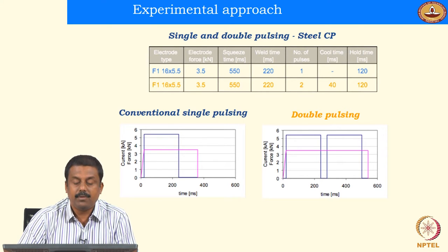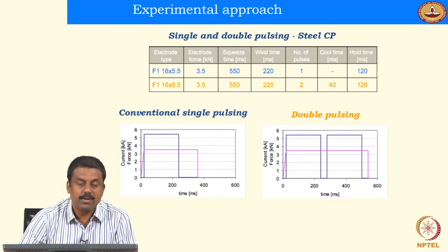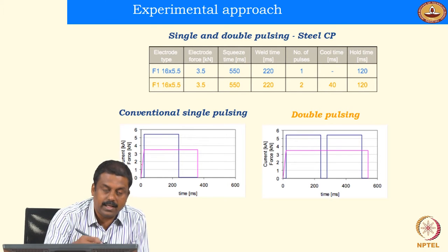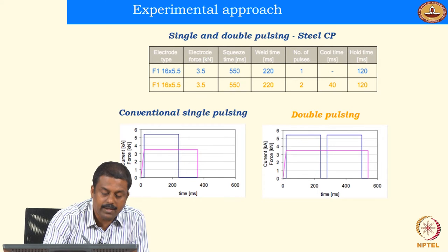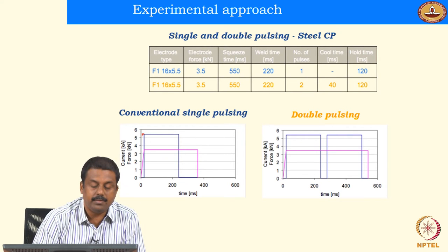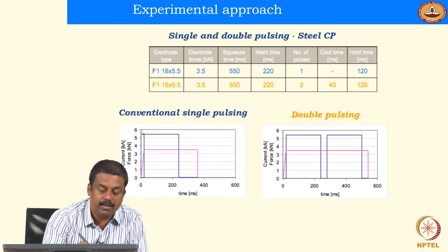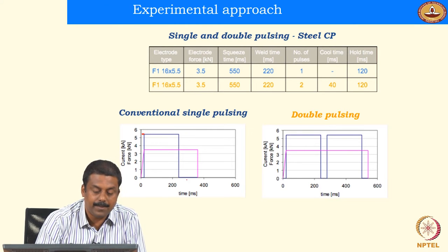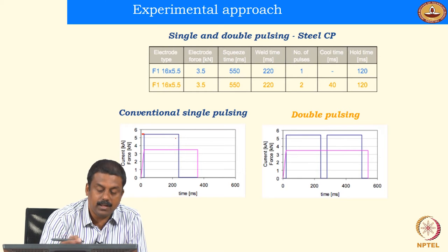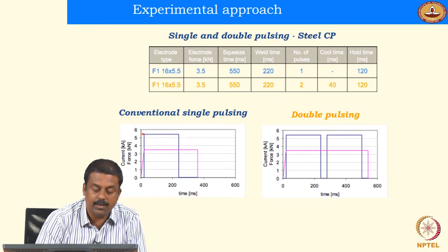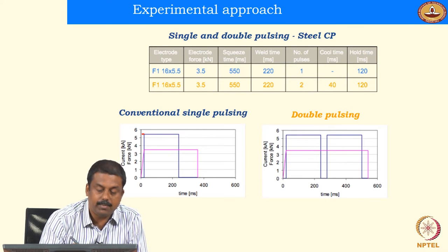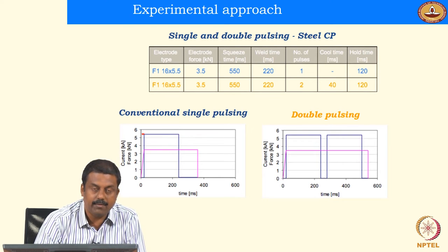So this modification, we can do by applying a second pulse during resistance spot welding. In conventional single pulse resistance spot welding, again recall our lectures on resistance spot welding, we have the current cycle where we give an amperage of over 5.5 to 6 kiloamperes, and we can recall that we can identify the actual current from the weld growth curves. We can apply an amount of load required to keep the faying interfaces together, and then we can play around with the pulsing parameters to achieve varying weld nugget size, right?